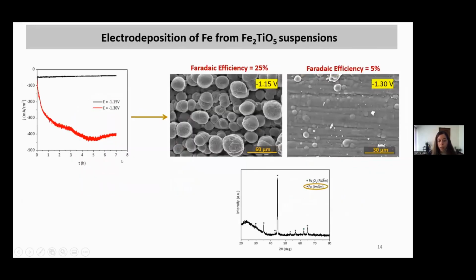So we also compared these results with the suspension mode. We applied the same potentials, -1.15 and -1.30 volts. You can see immediately the difference in current densities. This more cathodic polarization is clearly associated with hydrogen evolution. However, in both cases, we got metallic iron. We have here some magnetite phase, and this is just minor oxidation after the deposition because it's exposed to air. It's a very thin layer, so it oxidizes quite fast.